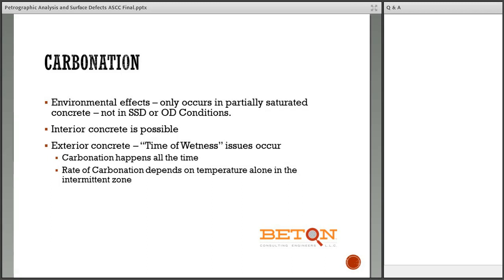If your concrete is oven dry or your concrete is saturated surface dry or wetter than that, then air can't get in. In interior concrete, it is possible to use carbonation to determine the age of the concrete, so long as you don't have something like someone mopping that concrete floor once a week. For exterior concrete, a statistic that the European Code calls the time of wetness, which is how frequently it rains, issues will come and stop carbonation at some point. You need to remember that carbonation happens all the time to concretes that aren't wet all the way through, including at the surface. And in that intermittent zone, the rate of carbonation is dependent only on the temperature. Intermittent zone being where there's some drying.